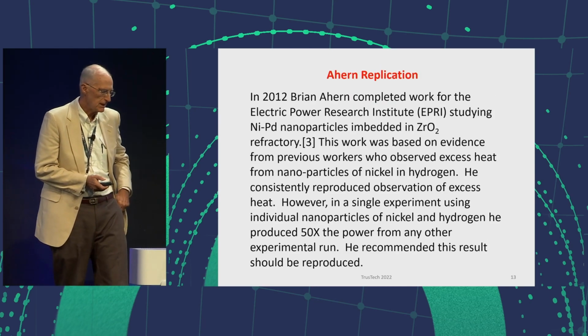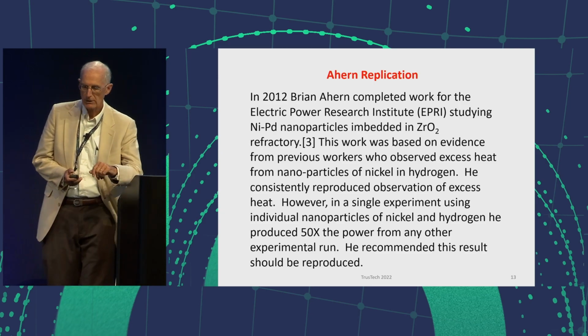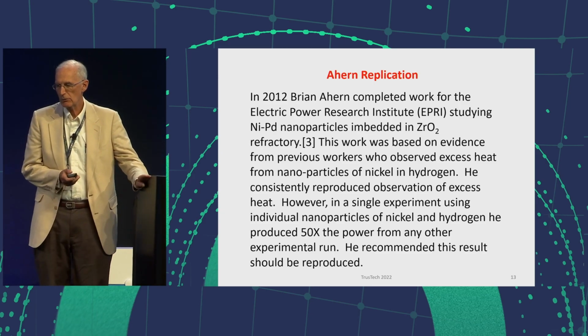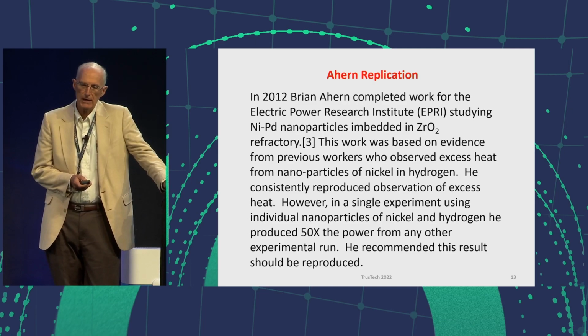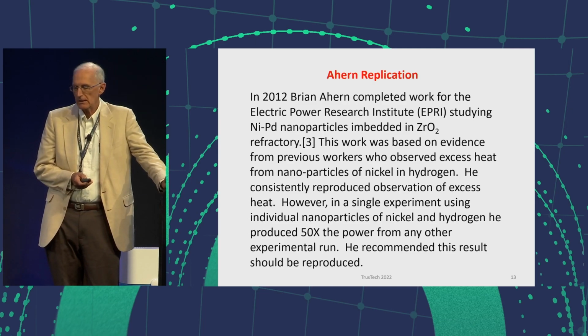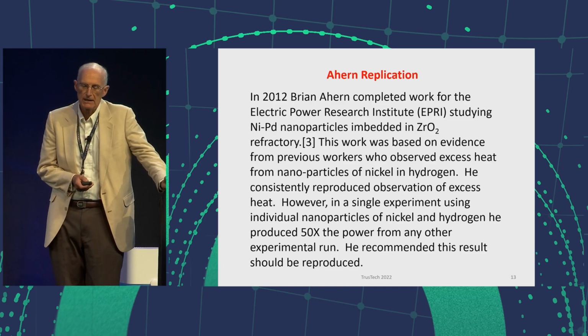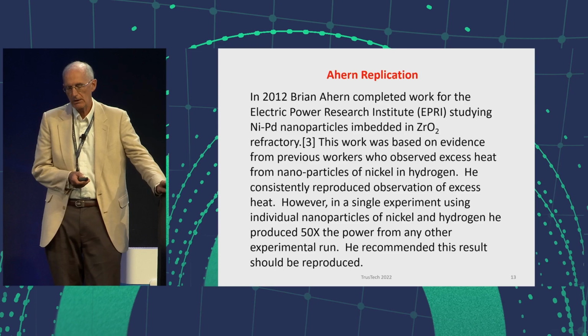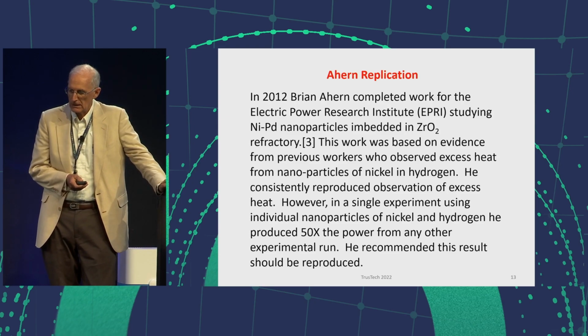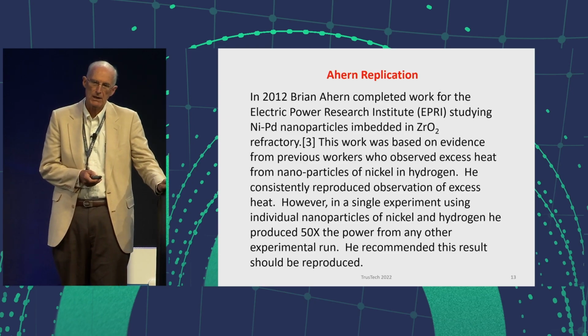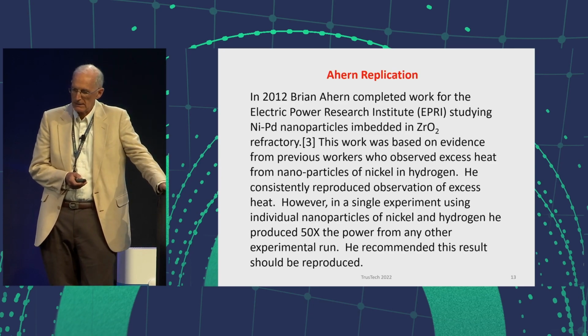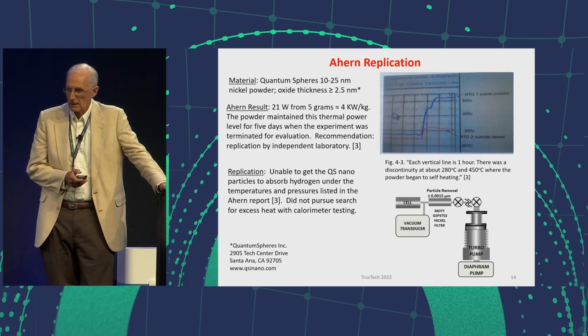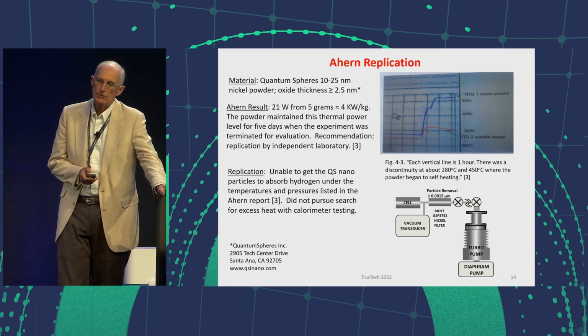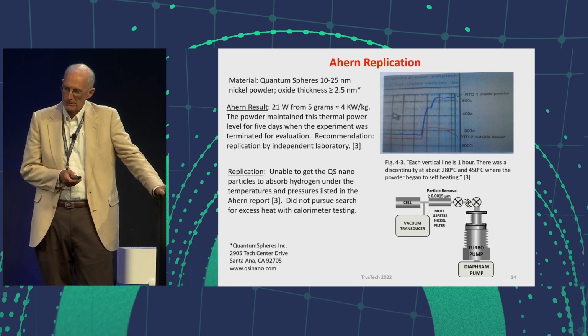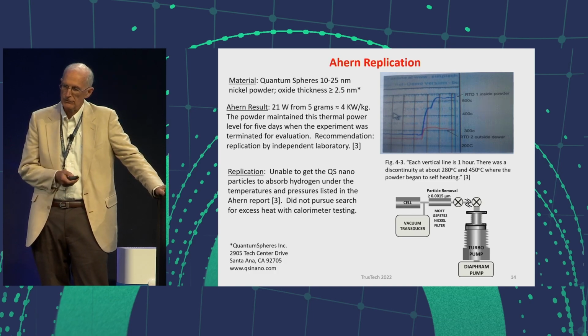So the second replication that I attempted was taken from an EPRI report written by Brian Ahern in 2012. He was doing a lot of studies of nanoparticles and of refractory zirconium oxide, but at the end of it, he did a study of pure nanoparticles of nickel in a cell, and he saw 50 times more power coming out from the other studies, and he recommended in that study that it should be replicated. I was able to obtain the exact material that he used, which is from a company called Quantum Spheres, which is referenced at the bottom here.